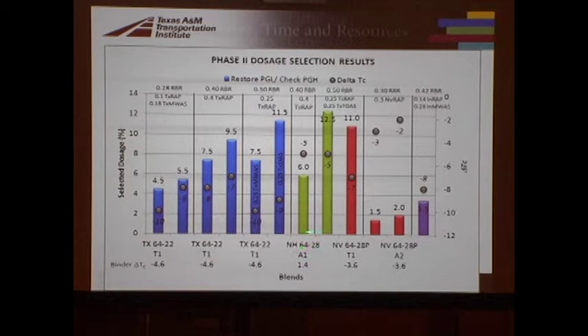The New Hampshire binder is in green. It starts out from a better place. It has a much better delta TC to start with, so it has room for those recycled materials. Then we have the red, which is the Nevada 64 minus 28 polymer modified binder. And from this line over to the left, this is all with Texas recycled materials. These two little short guys over here are with Nevada RAP only. So no RAS and much less aged RAP. So what you see here is, number one, it's a little bit better quality in terms of the base binder, but what you see is that the recycled materials are just not nearly as stiff, okay? They're just not nearly as stiff.